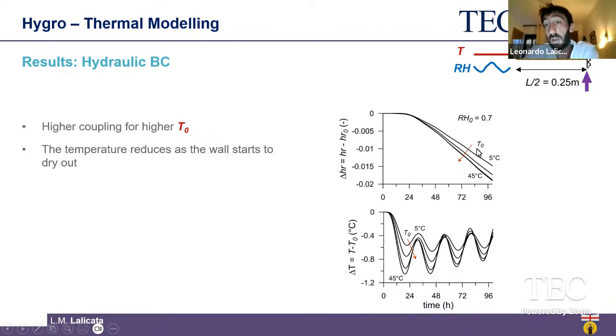And this process depends also on the initial values of the temperature in our model. But what is interesting here is the coupling term. So what happened to the temperature when we are imposing just a change in the relative humidity? What we get here is that in the first 100 hours of this simulation, we observed a reduction in temperature at this point of the model here, which is also a function of the initial temperature values, which means that the higher the temperature, the higher the coupling that we have in our models.